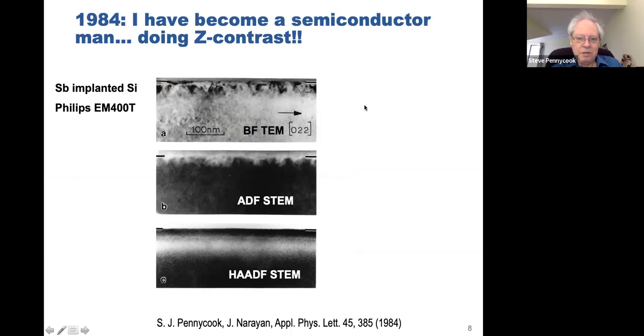But you can see with the Philips, we actually could get to a high angle detector just by going to a low camera length. And so here you have a regular TEM image of a cross section of antimony implanted silicon. You can see damage or defects in the near surface region, end of range damage. And in the regular ADF STEM, low angle ADF STEM, you still see the diffraction contrast dominates.